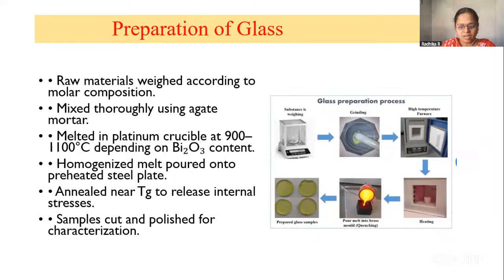are melted in platinum or alumina crucible at a temperature range of 900 to 1100 degrees centigrade, depending on the bismuth content. The homogenized melt is poured onto a preheated steel plate and annealed near the glass transition temperature, up to 250 degrees centigrade, to release the internal stresses. Samples are cut and polished for the characterizations.